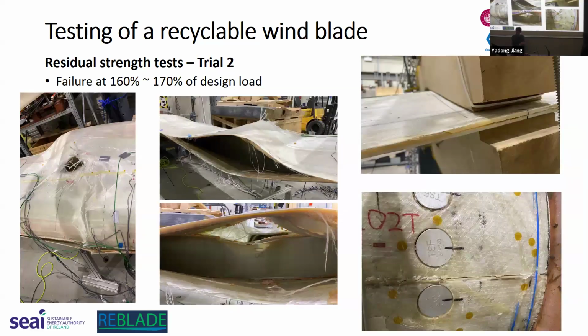Okay, so here are the failure mechanisms of the composite material. Here is a failure, a glass fiber failure at the center of the part. Besides that, there is a leading edge separation at the same location. And the trailing edge also separated because these two are bonded with adhesive. And if we look inside the blade, we can see there is a buckling of the web. So the web also failed. And here you can see the damaged adhesive of these two bonds, these two components.